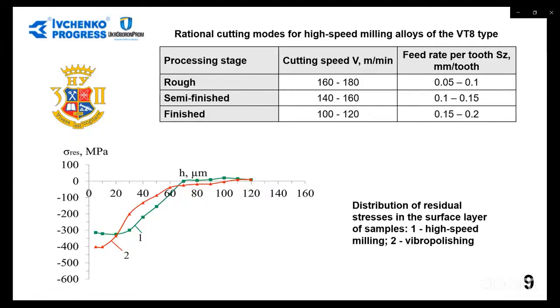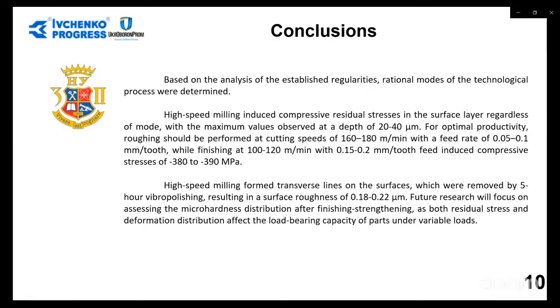Vibro polishing of the compressor blades allowed us to completely remove the regular micro-relief stitching from the previous high-speed milling and provide surface roughness within the array 0.18 to 0.22 micrometers for the pressure side and the array 0.22 to 0.36 micrometers for the suction side. Therefore, the finishing processing of the sample surface provided improvement of the surface layer quality. It was determined that vibro polishing with a rational combination of mode parameters resulted in a significant enhancement of residual stress level within the surface layer of the specimen. Based on the analysis of the established regularities, rational modes of the technological process were determined.